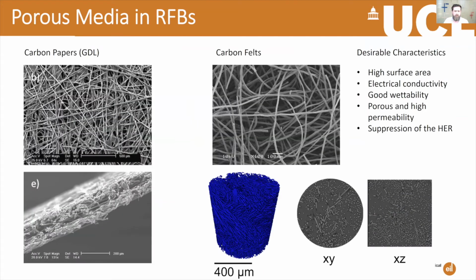Of course, because you're flowing electrolyte, you need to use porous media in flow batteries. And there's a variety of different porous media that gets used. Carbon papers, which are similar to the gas diffusion layers in fuel cells, are used quite a lot. And also carbon felts, which are a bit more of a 3D woven structure, normally woven polymers that are then carbonized into conductive carbons.